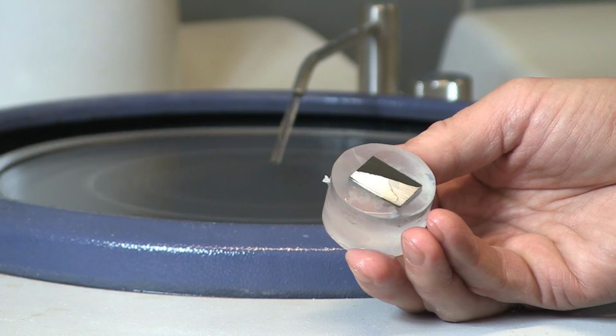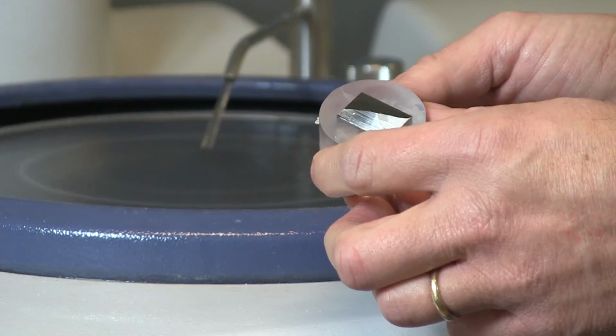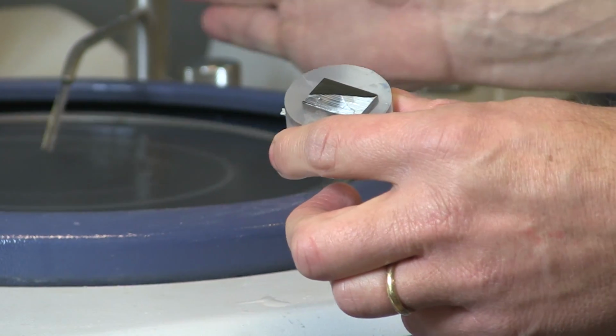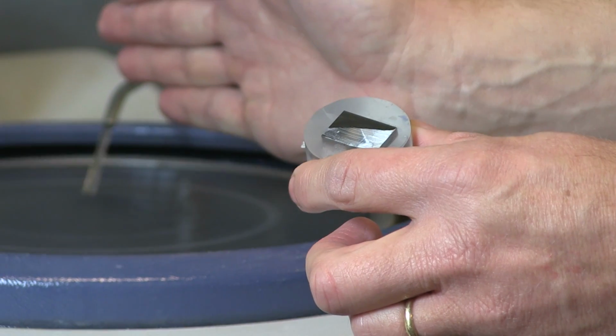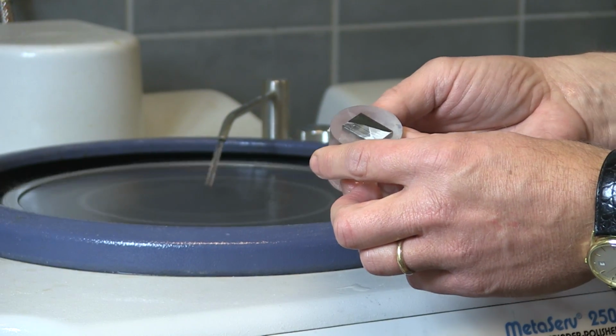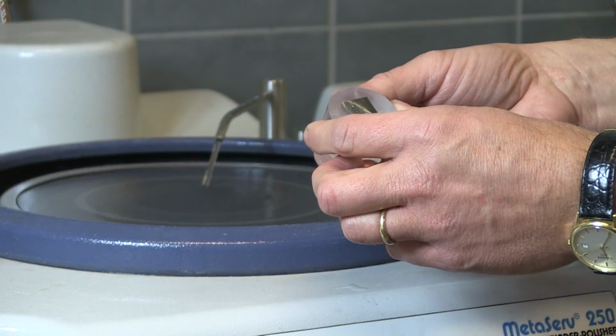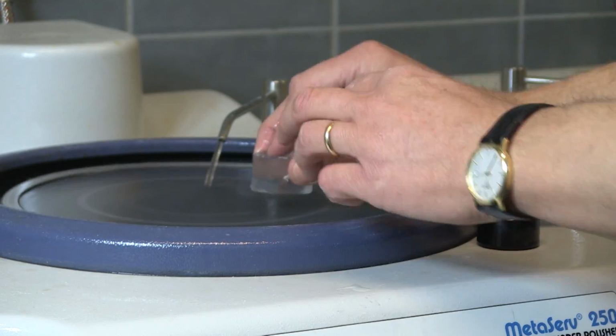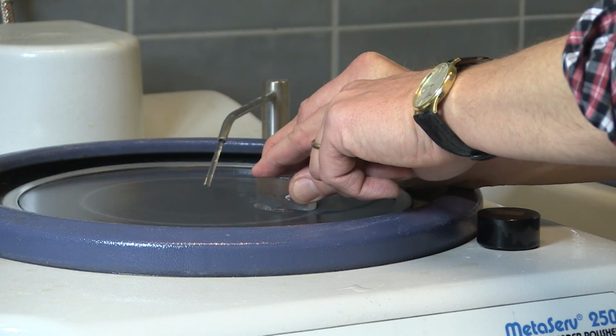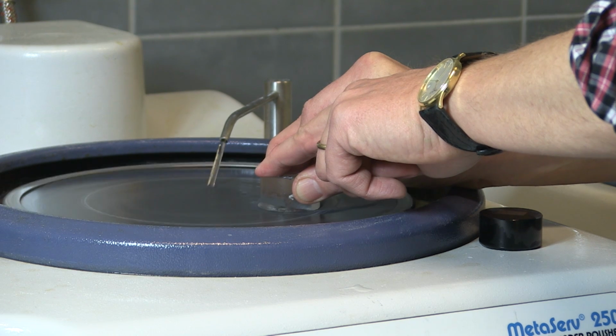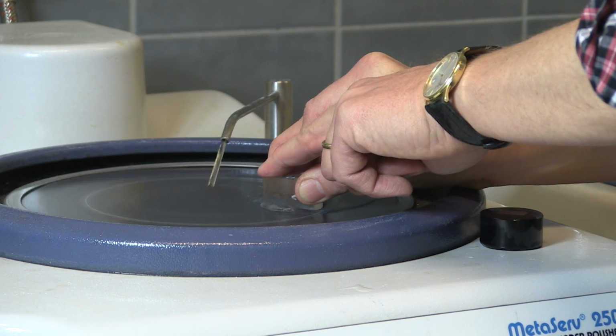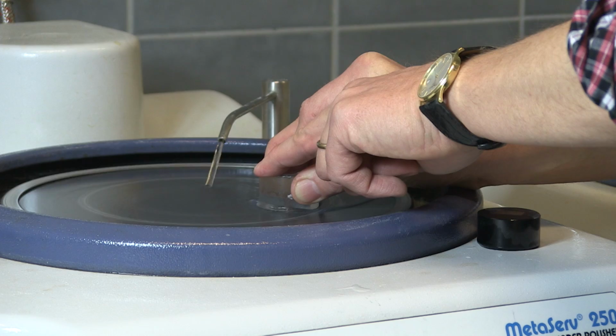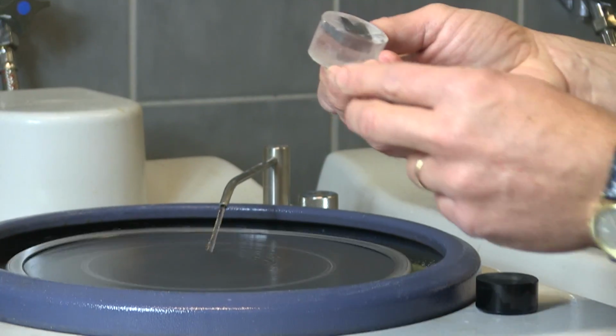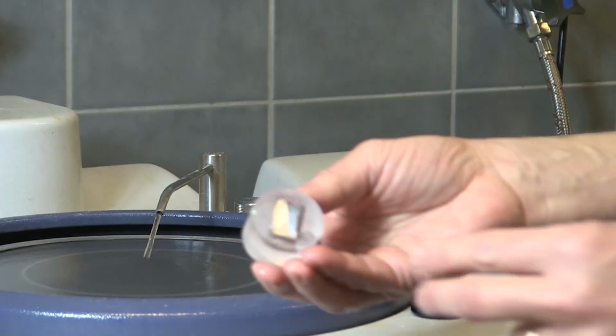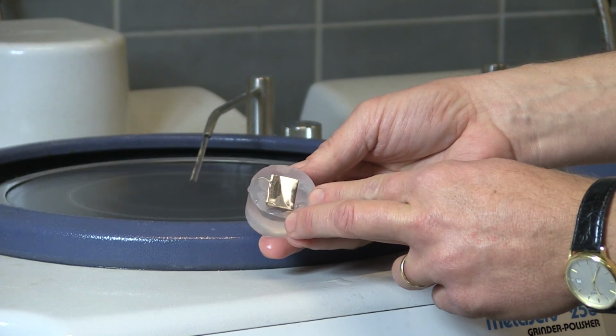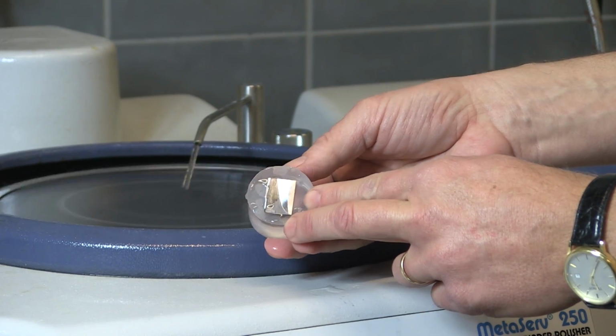The solution to this is, if you get it on finer papers, you should go back to more coarse papers. For instance, 240 grit paper. It's easier to repair then. And then do as I told you in the beginning, concentrate more on holding it flat than pressing. That will help you to repair the sample. So I won't finish it now, but remember, this can happen. It can look like that also. It will get better with training, of course.